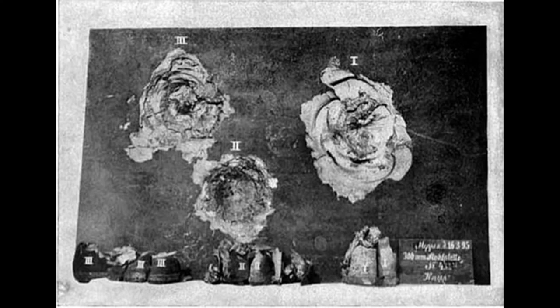Thus, despite the continually increasing power of guns, armour belts remained relatively static in thickness during the late 1890s and early 1900s, the Royal Navy's armoured belts, for instance, hovering at around 9 inches thickness on their Krupp armoured pre-dreadnoughts until the Lord Nelson class, and then of course Dreadnought herself. German battleships likewise remained at between 9 and 10 inches of thickness, and American and French vessels at around 11 inches of maximum thickness, as said, in a period where gun performance was climbing quickly.